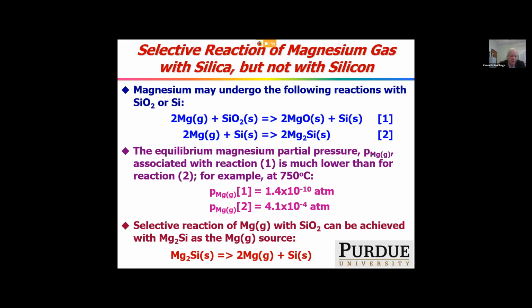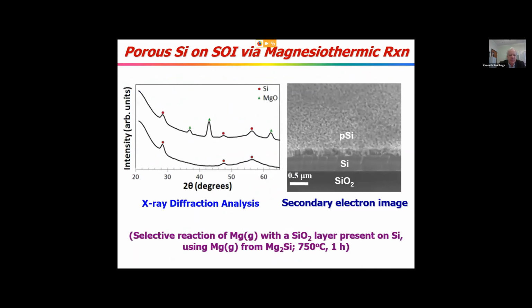If you heat it up, it will have a partial pressure of magnesium. It will have no desire to reform magnesium silicide, and that magnesium vapor pressure is more than enough to react with silica selectively to form silicon and not magnesium silicide. So that's what we did. And the top X-ray pattern you see on the left here has the mixture of two phases. We dissolved the MgO away.